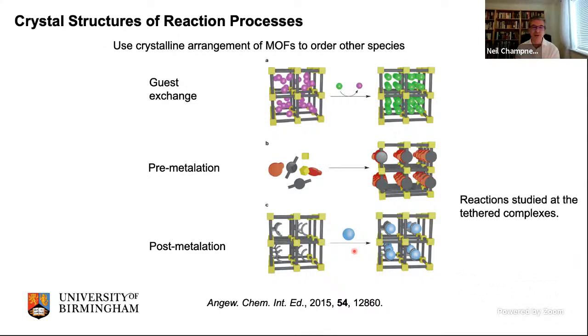For example, if you can imagine a framework structure, such as that shown here, and it has guest molecules sitting in the pores of the framework. That's represented by these purple balls. We can then exchange those purple balls for a different species, a green ball, and the green ball becomes ordered throughout the framework. And we can now determine the crystal structure of those new species, the green balls, because they are ordered in a crystalline arrangement. Now, this is the basis of Fujita's crystalline sponge approach.